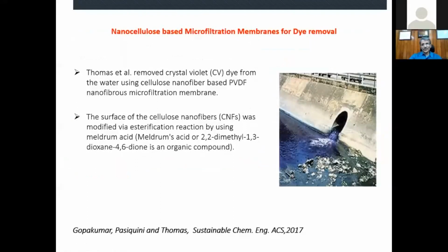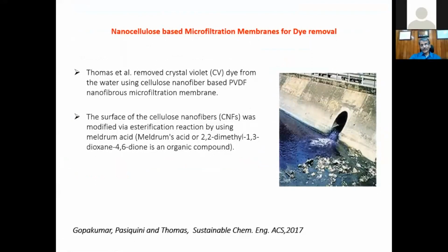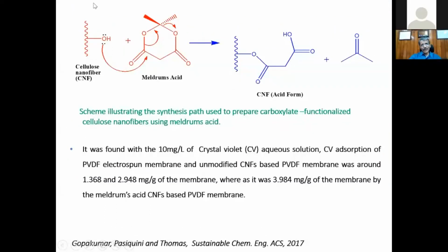At the top of that, you have an electrospun nanofibrous substrate. This is PVDF, the top one. You know what we have done? We have done a coating of nanocellulose on the surface. Okay? Spray coating. And what we try to do is we try to remove crystal violet dye. There are a lot of textile industries in India, they pump out this waste into river water. You can see the violet color of the water because of the crystal violet. We want to remove this very efficiently, and my PhD student did a small chemistry.